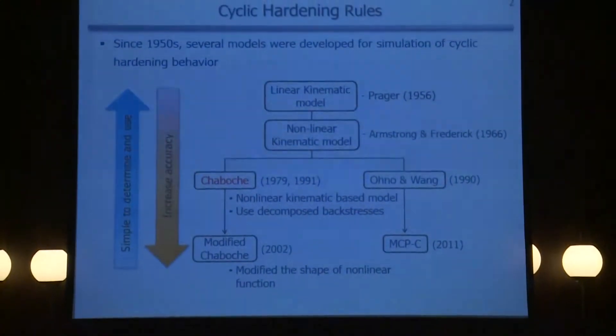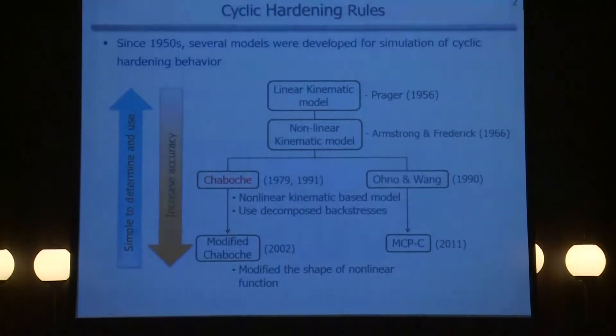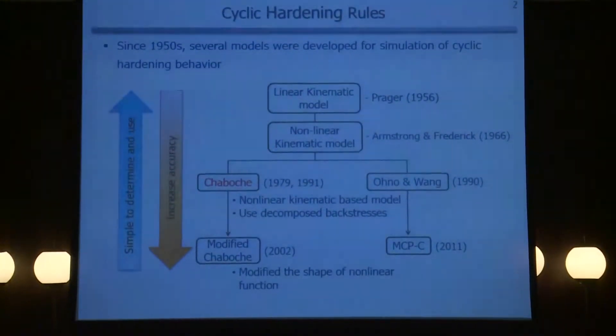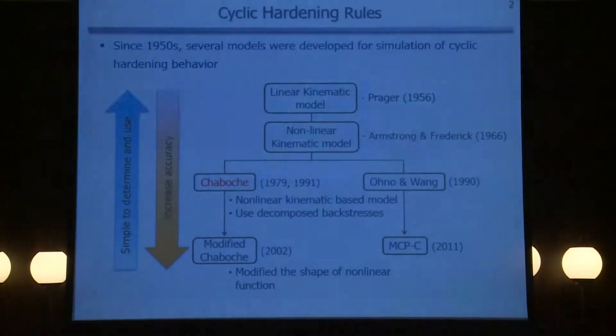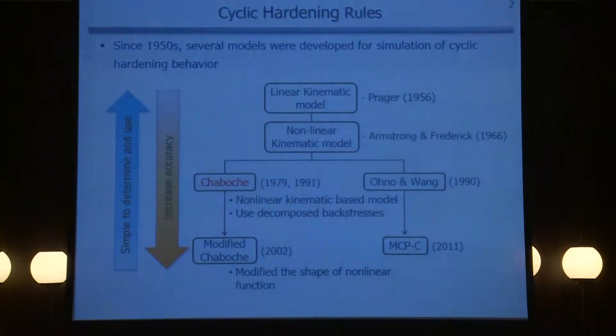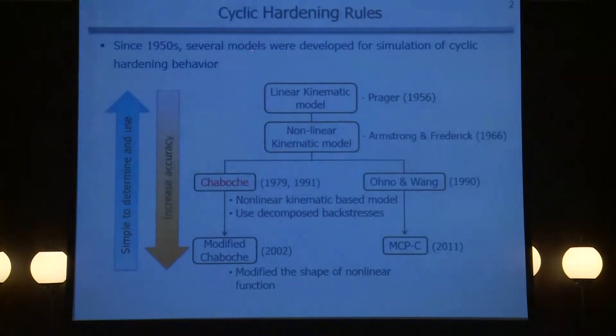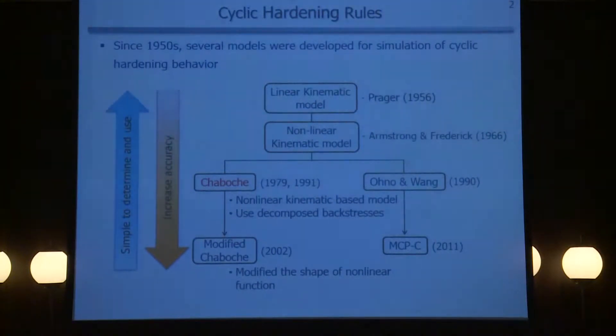Since the 1950s, several models were developed to simulate cyclic hardening behavior, from the linear kinematic model to the non-linear kinematic model, and then more complicated models such as the Chaboche model and the Ohno & Wang model. With simpler models, we can determine parameters easily, but they have limitations for more accurate simulation. So in this study, we use the Chaboche model for the cyclic hardening parameters.